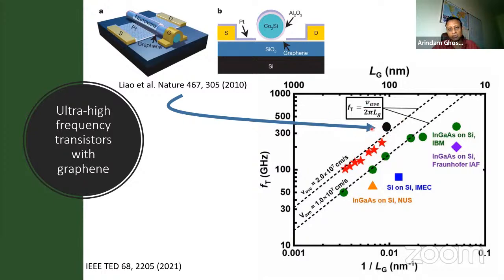Okay, and this frequency scale is called FT, which tells you how fast you can operate the device. In the case of graphene, at around 100 nanometer of gate length, you can see it is the fastest known transistor of about 300 gigahertz. Theoretically, this should be in the order of a terahertz or 1.4 terahertz, but that has not been achieved so far. So this is one aspect of the unique electrical property of graphene.